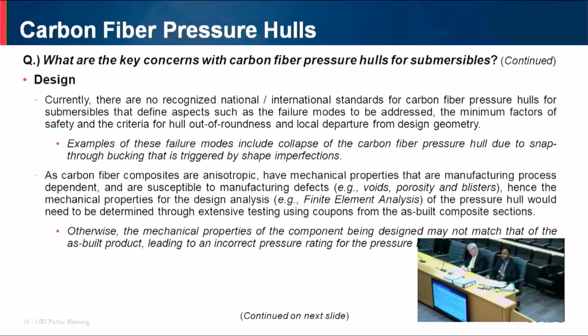Okay. Snap-through buckling is different from traditional buckling, which is caused by progressive overpressurization of the pressure hull beyond its design depth. When snap-through buckling occurs, it causes instantaneous delamination and instantaneous collapse of the pressure hull, which can occur in less than a millisecond. Okay. So if you have sensors for real-time monitoring, they will not pick up any signs of this failure before it occurs. Snap-through buckling is a phenomenon that is not yet well understood. Additional theoretical and experimental research is needed to determine what factors cause this failure mode, what factors of safety are needed to avoid it, and what we need to do to guard against it. So this is something that is not addressed in international standards. It is not well understood. Nevertheless, this effect has been observed, and we need further research and testing in this area.